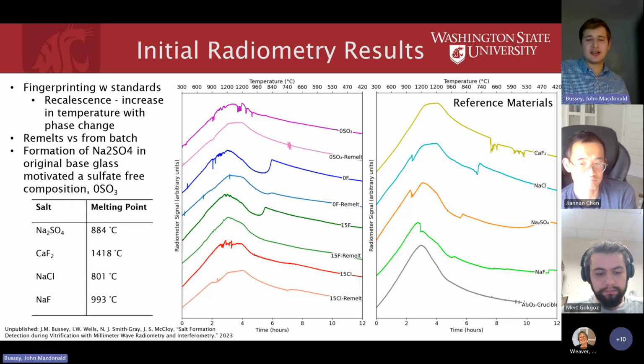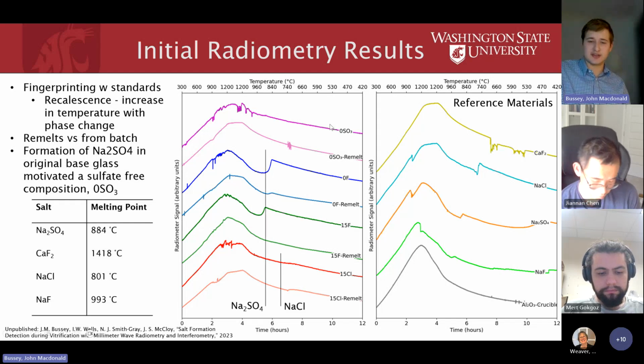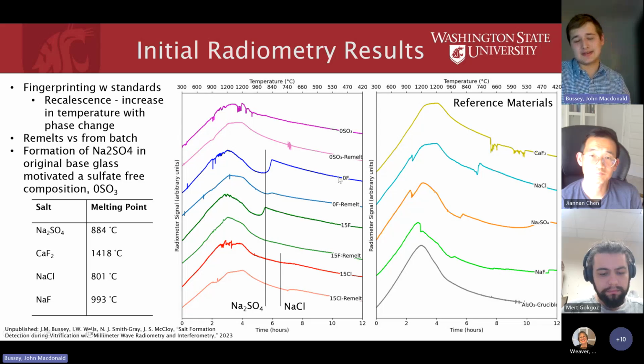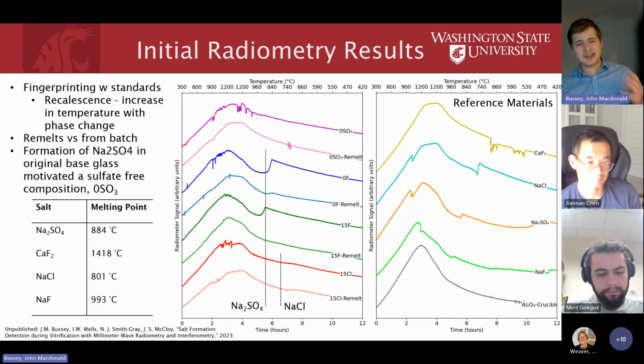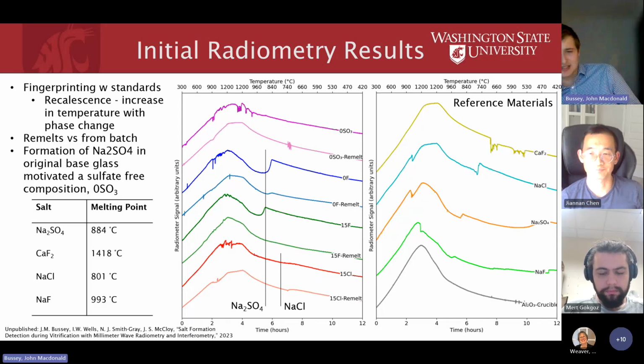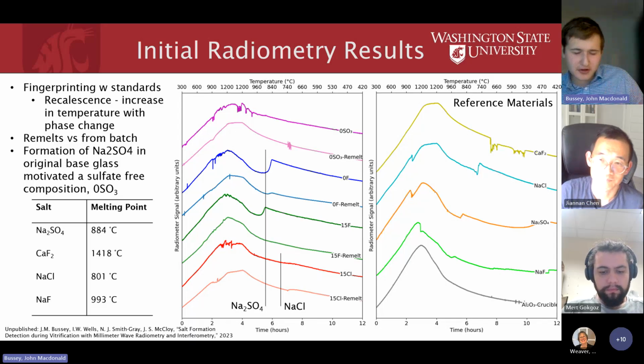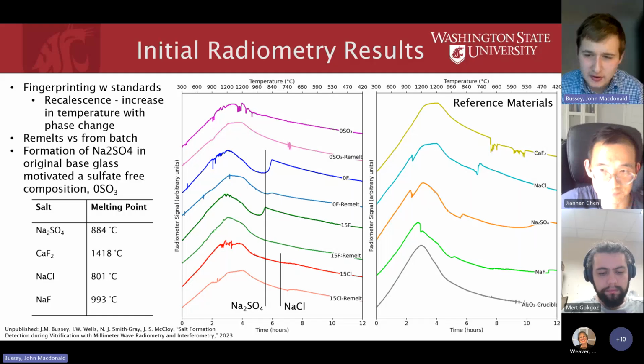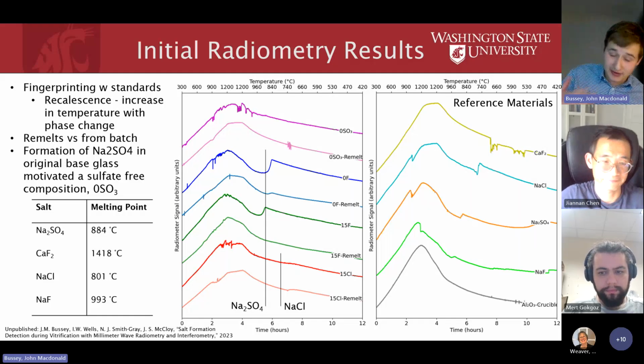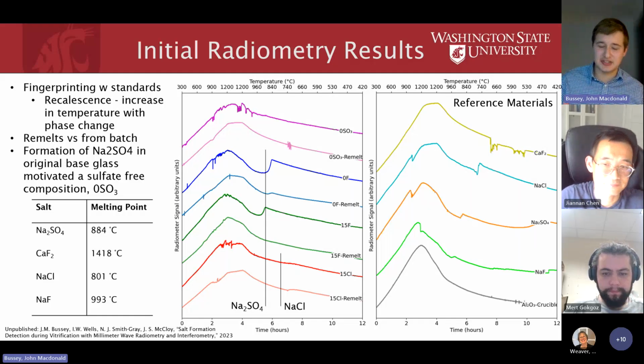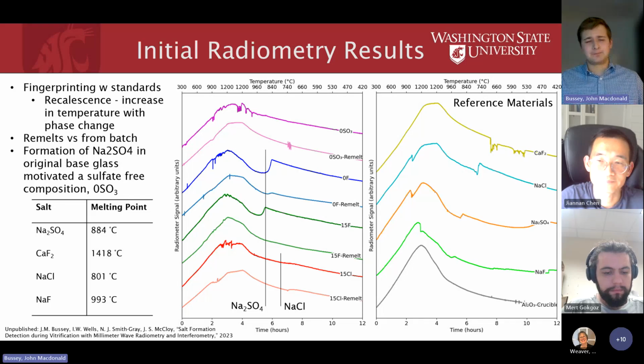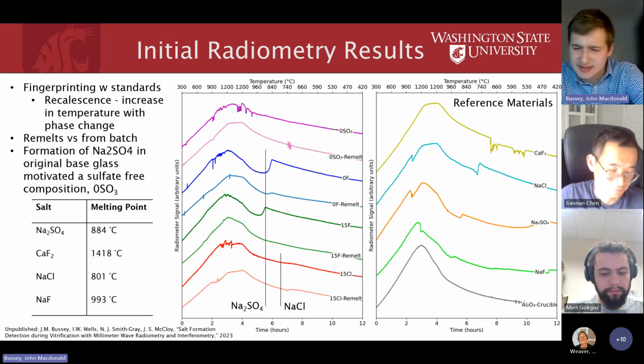And what we saw is that in the glasses that formed a salt, namely the fluorine, chlorine, and the one that just formed sulfate, we see fairly good agreement. Probably the easiest thing to tell is this recoalescence behavior, and we see fairly good agreement between the salt crystallizate, the freezing point, and the values that we observe. And so this is expected.